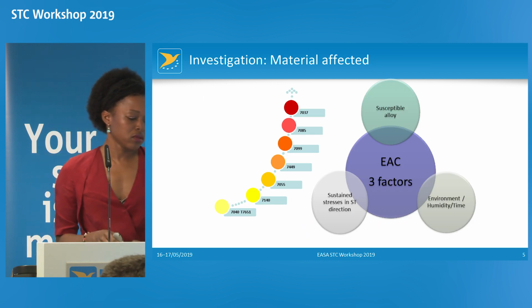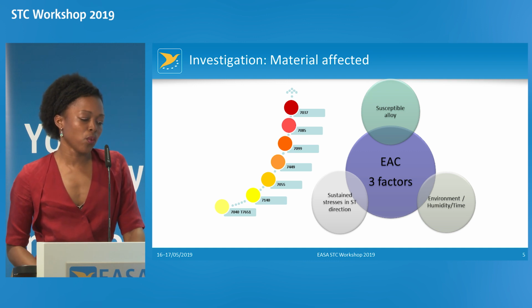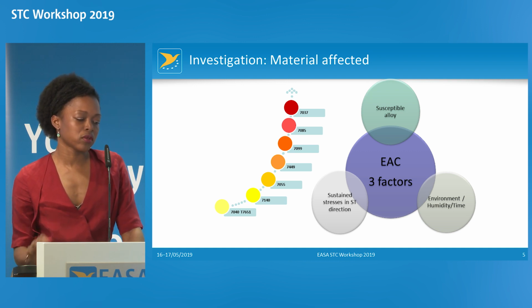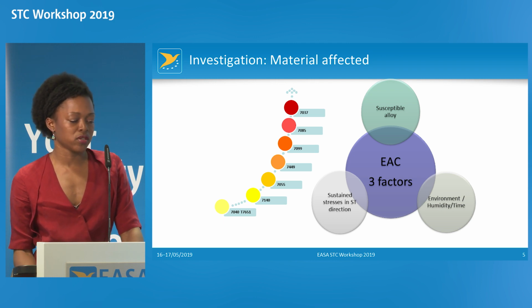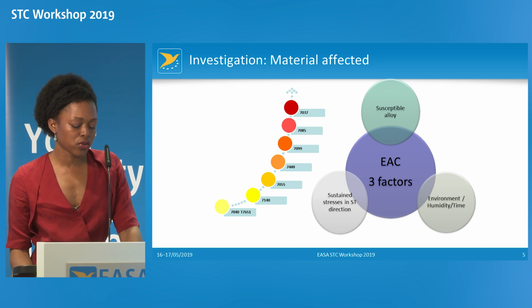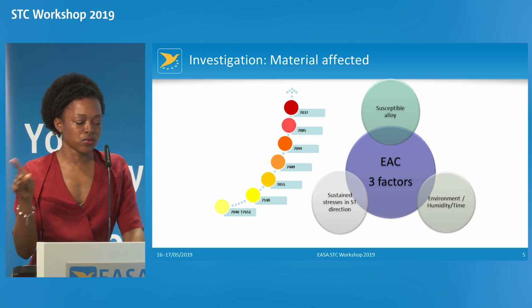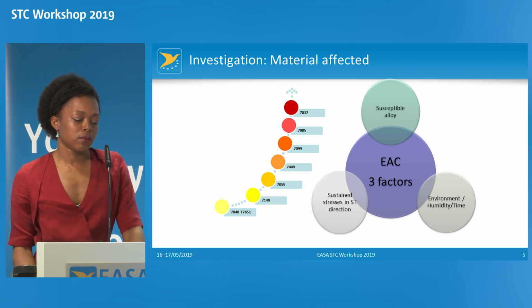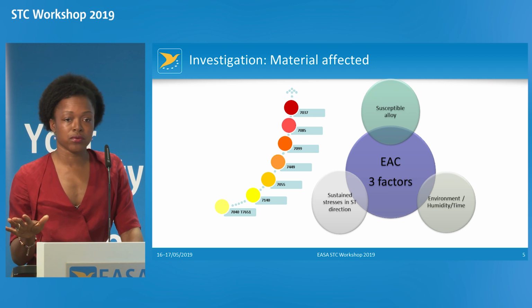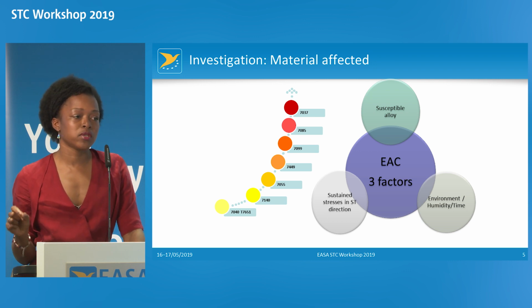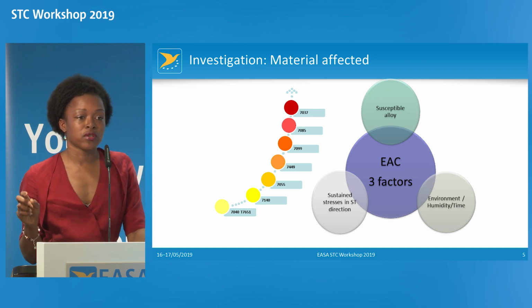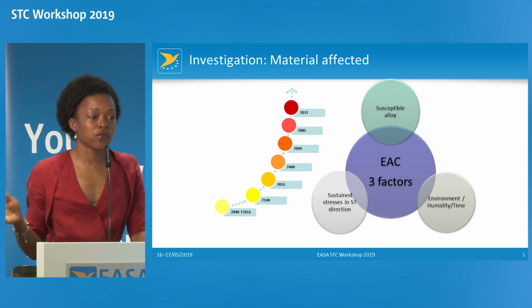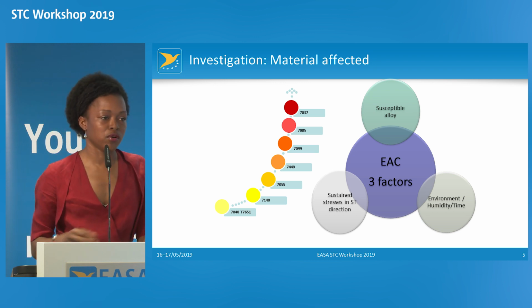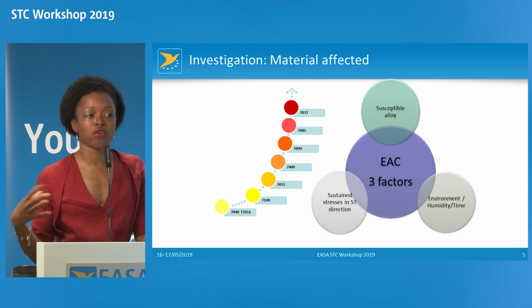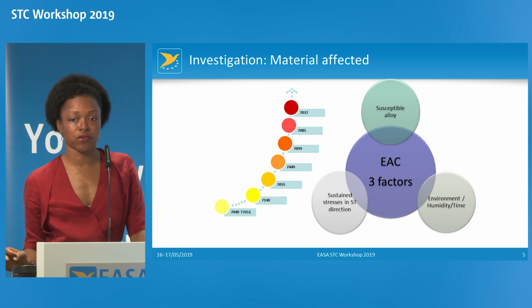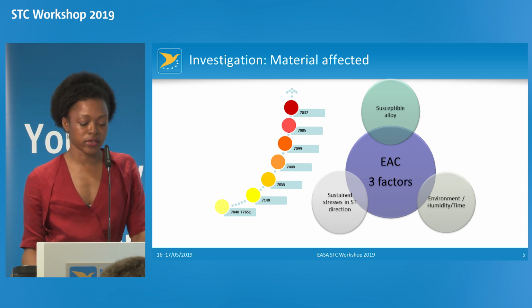On this slide, you can see a list of materials showing which references are sensitive to this form of EAC. As you see, they are aluminum alloys of the 7000 series. From yellow to red, you have the range of sensitiveness. You need three parameters to exhibit this issue. First, the susceptible alloy. Second, sustained stress in the short transverse direction. The third parameter is some level of environmental condition, humidity, and it develops with time. It's not related to cycles, nothing to do with fatigue. It's really exposure and time related.